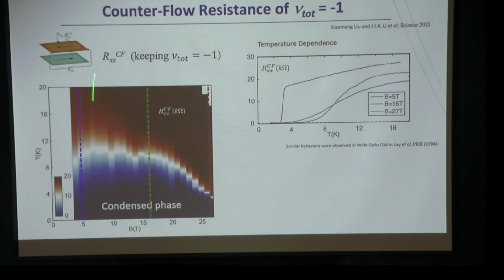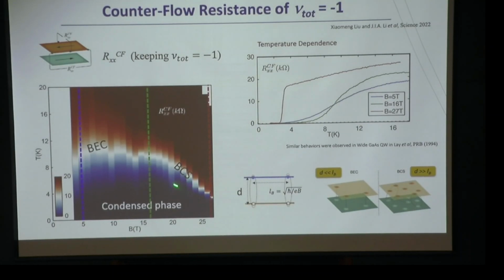Particularly, if I just make a cross-cut at constant magnetic field, a high magnetic field cut through there, at finite temperature there is finite counter-flow resistance that turns into zero resistance at low temperature. Now look at the flow. If I just hold this, not counter-flow resistance, but just resistance, what does it look like? This will look like superconducting conditions. Indeed, this region is related to, and the transition can be viewed as, a BCS-like transition, while as you go to lower magnetic field, where the excitons are well separated, the transition turns into a BEC type of transition with a nice crossover, you can see. Right. So this kind of phase diagram, what the audience actually expected, can be experimentally proven in this type of geometry.